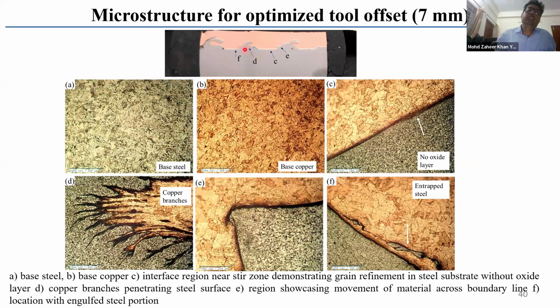This is not only macroscopic bulging that has anchoring that has taken place, but as you can see at the magnified level, there is microscopic bonding that has taken place between the two materials. But what is important to note over here is that the mild steel is not mixed with the copper on the top layer. Then, of course, some mechanical tests were performed, like hardness was carried out, tensile testing was carried